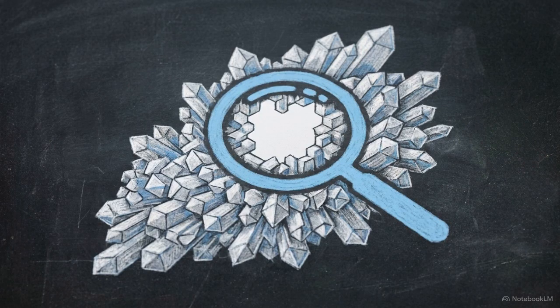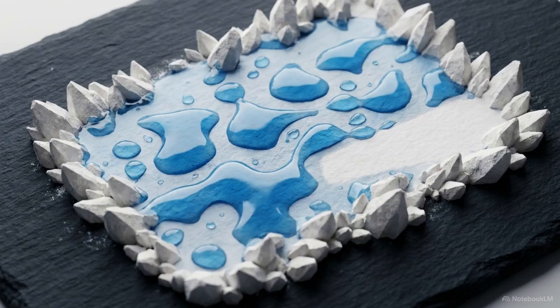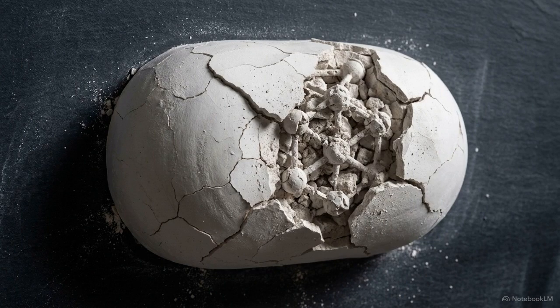This creates a severe amplification effect. If a drug powder is only 0.5% amorphous and it absorbs just 0.5% total moisture, that water doesn't spread out evenly. It concentrates entirely in the amorphous regions, creating a highly reactive, localized 50-50 ratio of water to solid. Those trace amounts of absorbed water act as localized thermodynamic catalysts. They rapidly trigger catastrophic chemical degradation and physical collapse across the entire formulation.